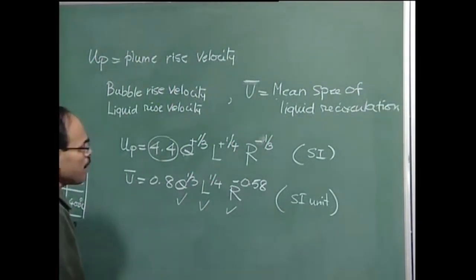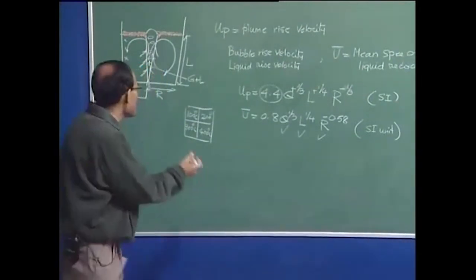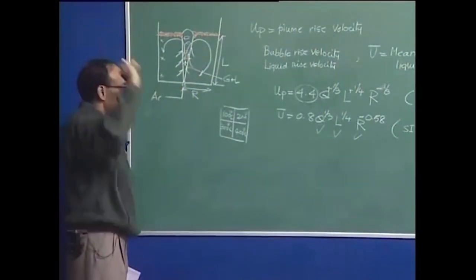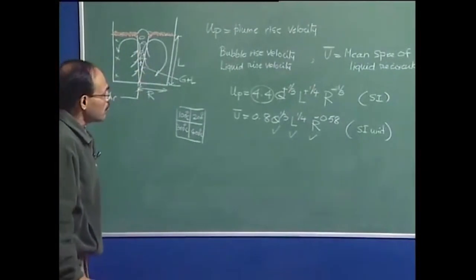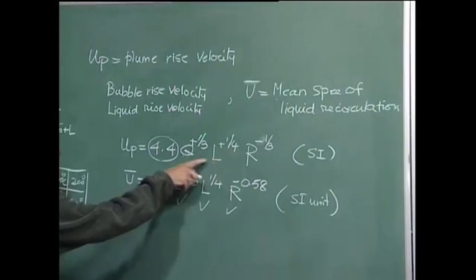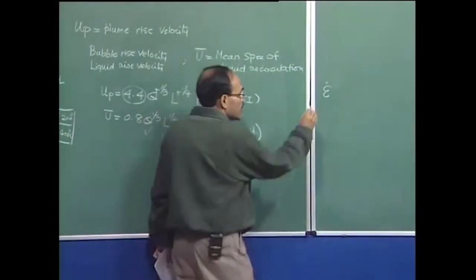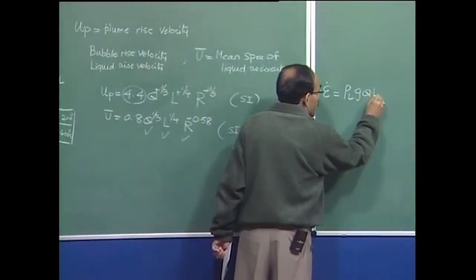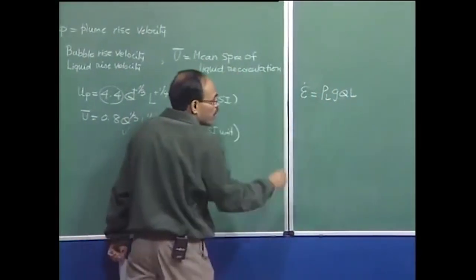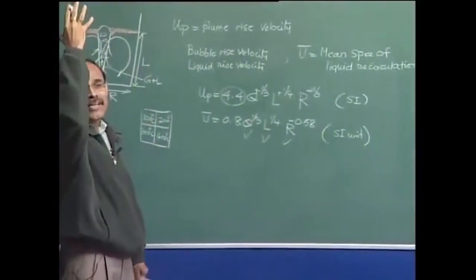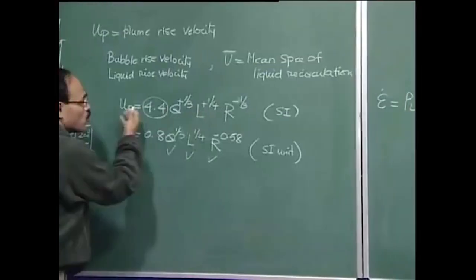These correlations apply under typical ladle metallurgy steelmaking conditions and cannot be applied to very large flow rate situations, extremely shallow baths, or extremely tall vessels. The potential energy input rate, denoted ε̇, equals ρ_liquid × g × Q × L. This tells us that if we increase the gas volumetric flow rate or the depth of liquid, the rate of energy supply increases, meaning more energy means more recirculation — which is reflected in the plume rise velocity formula as well.